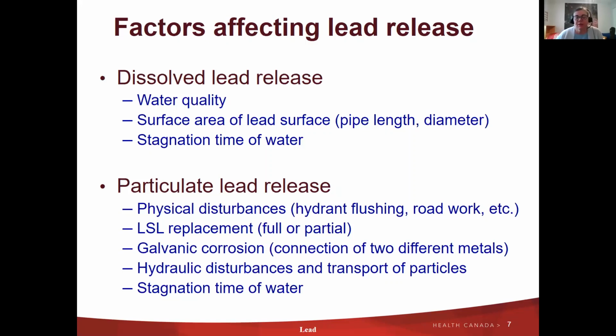So particulate lead release comes from physical disturbances. If there's hydrant flushing going on, road work, anything that vibrates a lead service, that can impact it. With lead service line replacement, whether full or partial, the protective scales that are inside the lead service can sometimes come off as small particles. You might get galvanic corrosion. So if you're getting the connection of two different metals, for example, if you're replacing one part of a lead service line with copper, but you've maintained that lead service on the other side of the connection, and that connection is brass, then there's galvanic corrosion that can happen there.